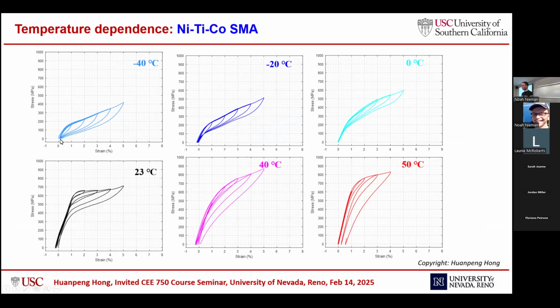Unloading from 5%, the residual strain is very close to 0. That means as the temperature pulls down to minus 40 Celsius, this material still exhibits around 5% of strain recovery capacity. This is really advantageous for bridge applications in cold regions.